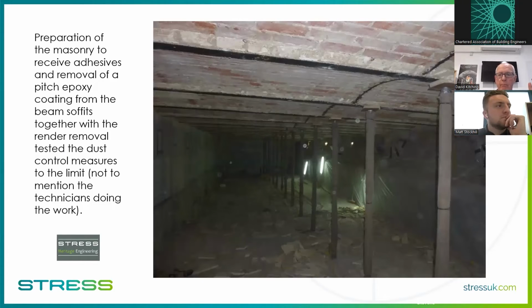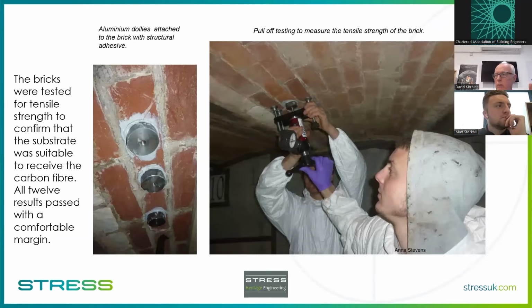So we cleaned it all up. We then carried out some pull-off tests. This is standard for every job, and you dot around, have a look at various parts of it just to make sure that you're getting that pull-off strength. In this case, obviously, you're testing the surface of the brickwork to see whether it will actually take the sort of bond strength required. So for those of you who don't know, the minimum bond strength you need to fully mobilize the carbon fibre is